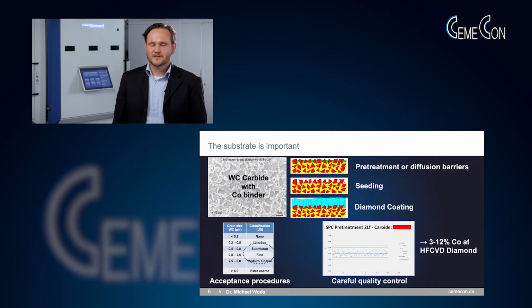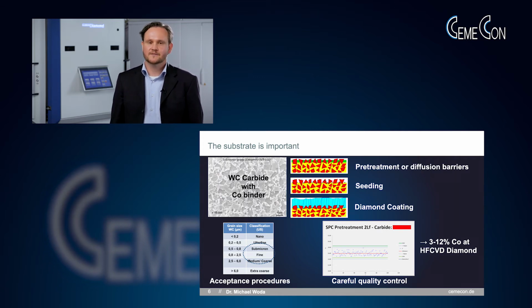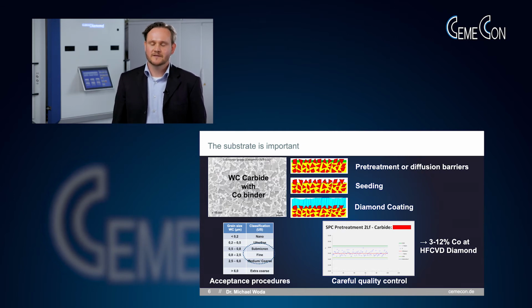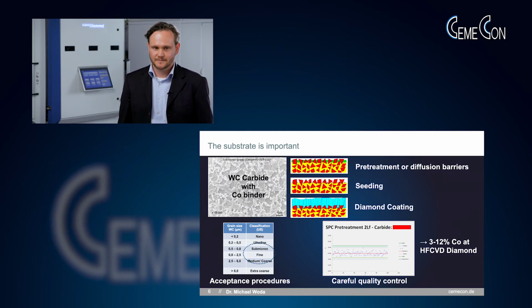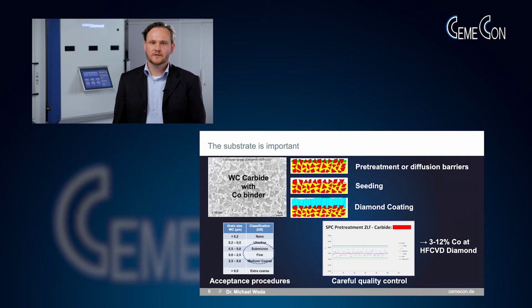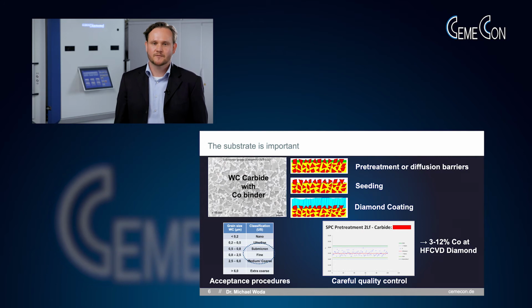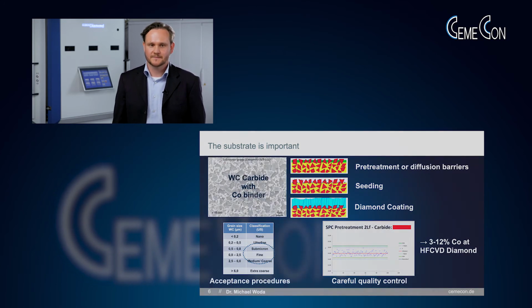However, it is possible to fulfill this task by applying careful acceptance procedures as well as doing careful quality control in a continuous manner. So we are able to coat cobalt-containing carbides with a range of 3 to 12% of cobalt content.